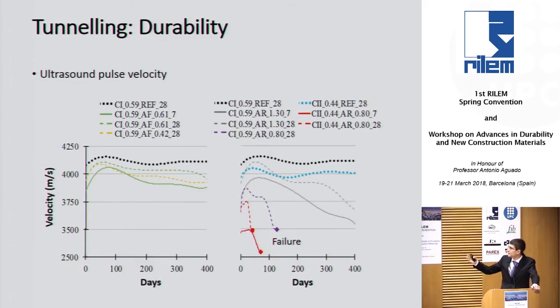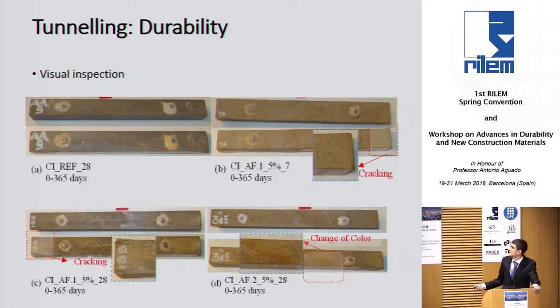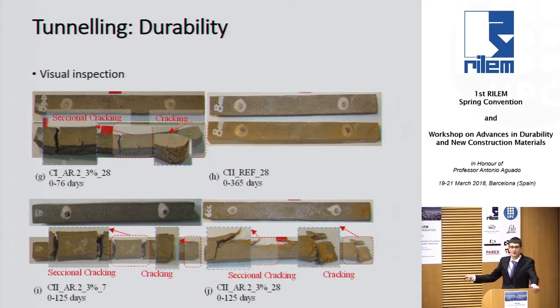Right? So then the ultrasound velocity measurement and the microstructural analysis confirmed the damage of the specimens. And when we started analyzing the specimens, we saw that, for instance, the reference didn't present significant damage after 365 days of exposition. The alkali-free, yes, showed small cracks, but the alkali-rich gave this result.